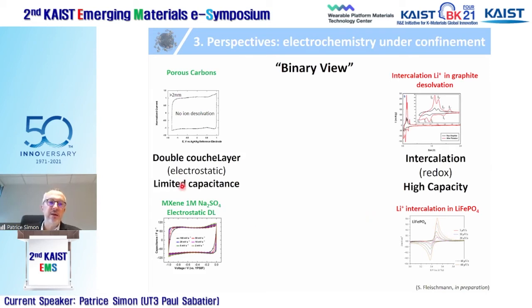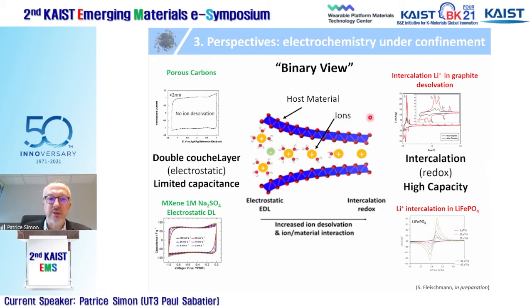So this process is purely electrostatic, limited capacitance, but very fast. And this process is purely redox, high capacity, but slow. But I would say that if you put this kind of sketch, where it's a host 2D material, a cross section, we could say that when the 2D layers are separated by a large enough distance, you can adsorb ions fully solvated here. However, when you decrease the distance between the 2D layers, then little by little you desolvate the ions more and more, and you can end up at this extreme situation represented by the redox intercalation process. High capacity, limited power.